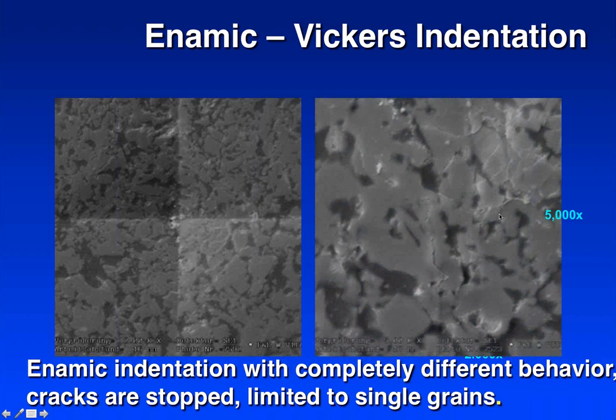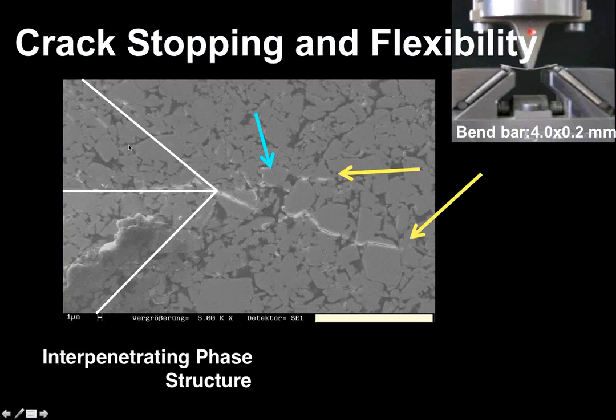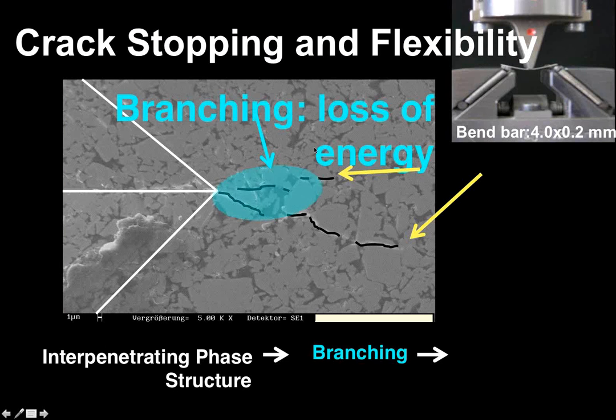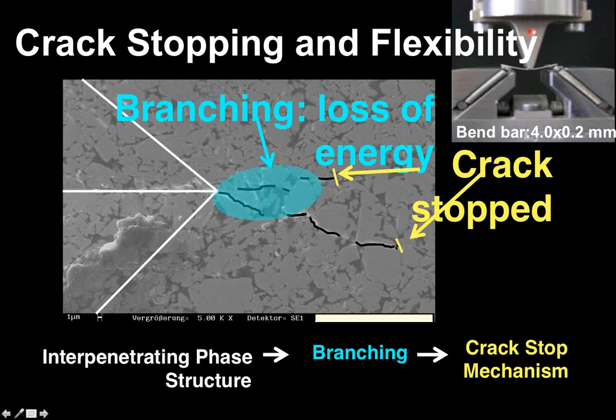There are some cracks that developed here, but the way the network is connected with the polymer and the ceramic, you get some branching of that cracking, and eventually the cracks stop at the polymer. So if we take a look at where the indentation is, this is the apex of one of the indentations. We see some cracking here, some branching as the crack tries to go through the material and cause it to fail. Energy is taken away from the crack, and eventually the polymer tends to absorb the energy and completely stop it.